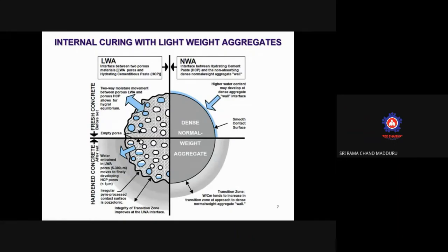But these lightweight aggregates can be used for low strength concretes only. In case of high strength concrete, what happens? As Rajeshwari ma'am is explaining about transgranular failure as well as intergranular failure, in high strength concrete the crack passes through the aggregates. When the crack passes through the aggregate, these lightweight aggregates have lesser strength, so definitely it will lead to decreased strength properties. So for high strength concretes, using lightweight aggregate is not a proper solution.